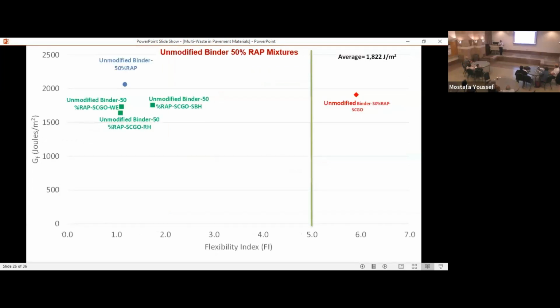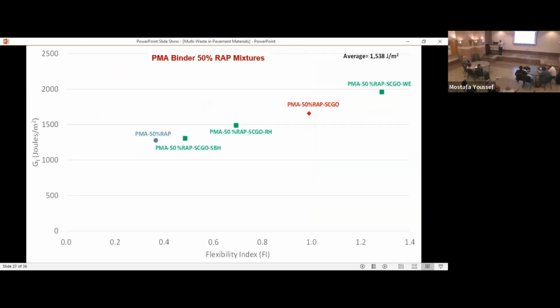Increasing the RAP, again, as I said, aged binder is highly brittle, so prone to cracking. You will notice that the range of performance for the flexibility index is already very low, and most of the mixes are not meeting the limit. The only one that is meeting the expected limit, which is not a standard limit but one recommended by the developers of this test, is the unmodified 50% RAP with the food waste oil. The presence of the ash in our case seems to have dropped the flexibility, but the oil itself has maintained some of that flexibility at 50% RAP. With polymer modified, none of the mixes matched. So it seems that we have been pushing the limits.